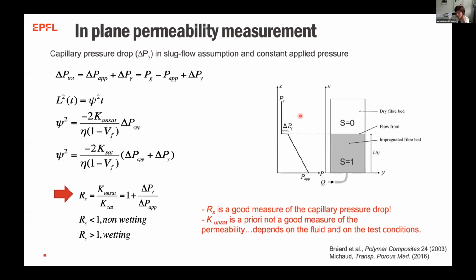So if we do a bit of calculations here, you know that the real delta P total is the one that takes into account delta P gamma, the capillary pressure drop. So the slope that we measured for L square versus T, when we find the K unsat, we use only the normal delta P. When we do the K sat, if we could do it, it needs to take into account the delta P gamma. So if we divide this one by this one, we have a ratio of K unsat over K sat that a lot of people have talked about.